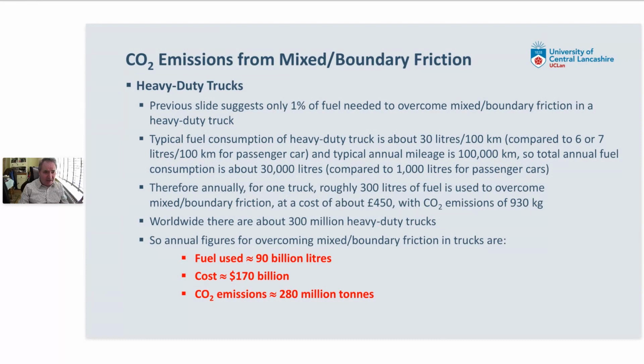And again, worldwide, there are about 300 million heavy-duty trucks. So when you do the sums, you actually find that the figure for a heavy-duty truck for overcoming mixed and boundary friction, in terms of both amounts of fuel used and finance and CO2 emissions, is actually higher than the numbers coming from passenger cars, even though the amount of mixed and boundary friction is actually lower in the heavy-duty truck.